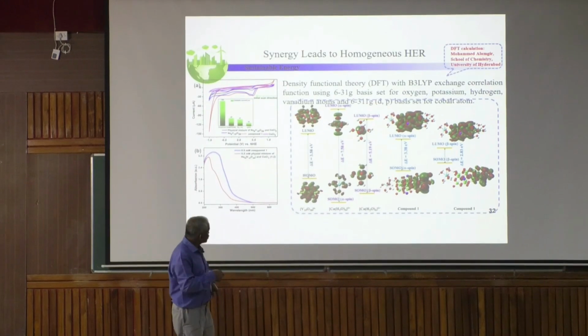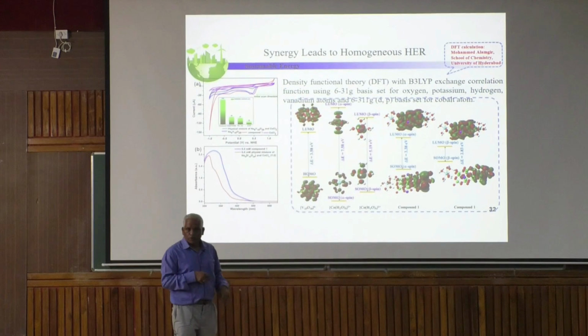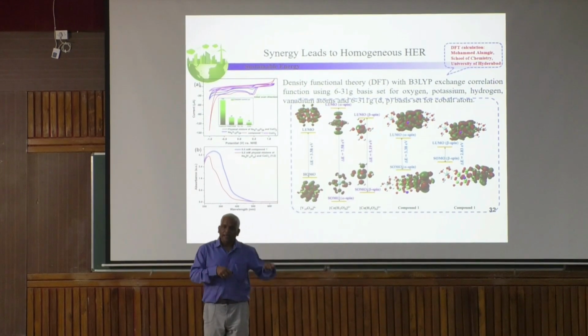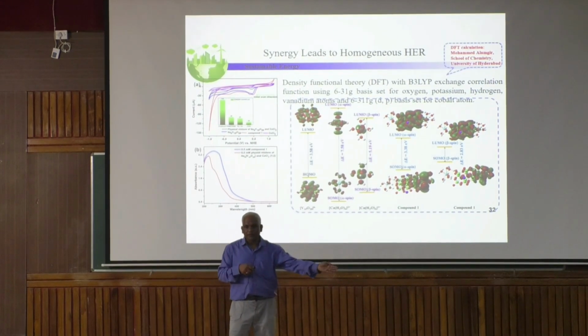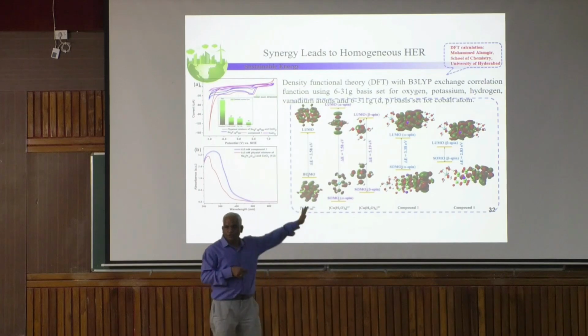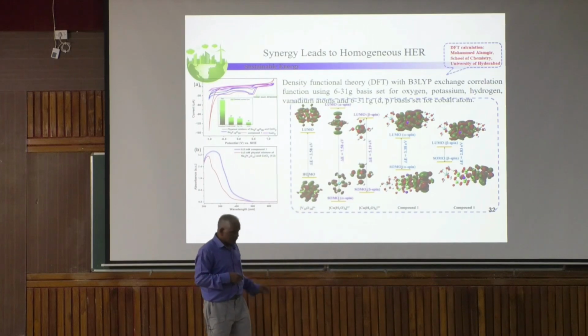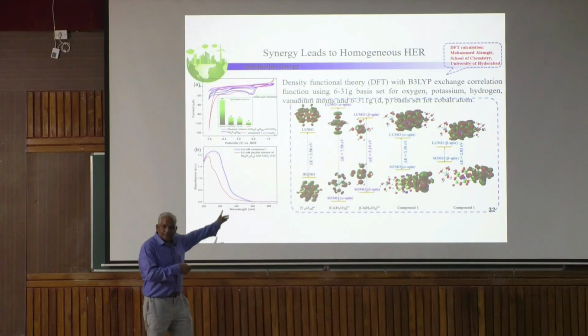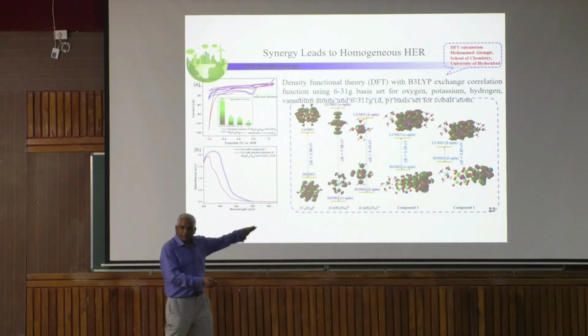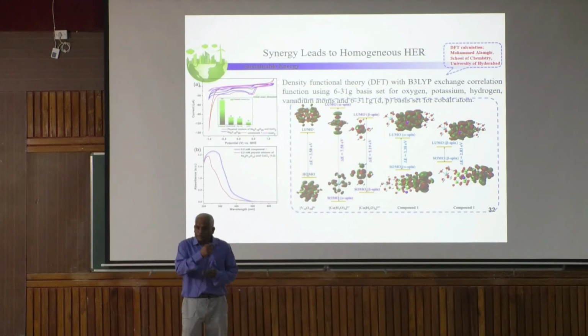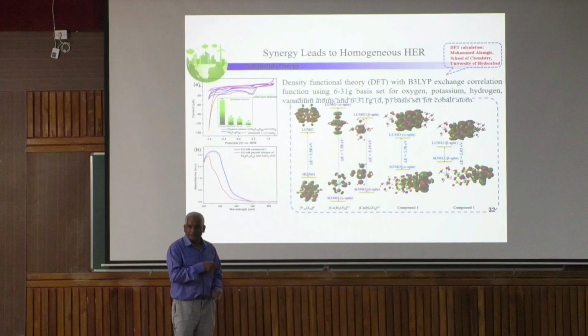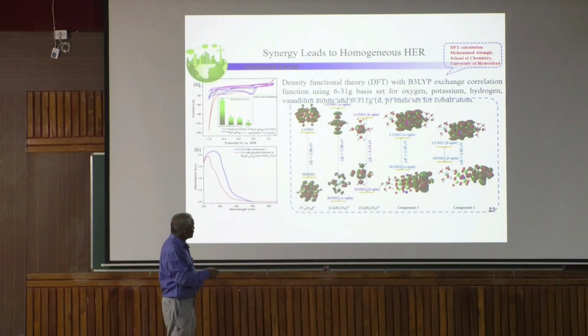And we believe that electron goes to cobalt. Cobalt 2 becomes cobalt 1, and then cobalt 1 reduces the water to hydrogen. This is from the theory. So that means synergy is definitely established, because as I told you, such a compound doesn't give water reduction, cobalt as such doesn't give water reduction, even a physical mixture doesn't give. That means a physical mixture doesn't establish synergy, because hydrogen bonding establishes the synergy, and finally we can get hydrogen.